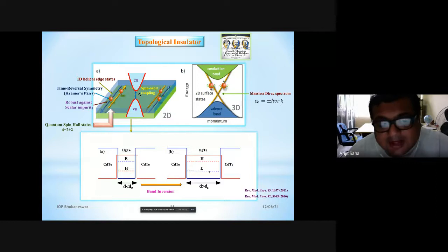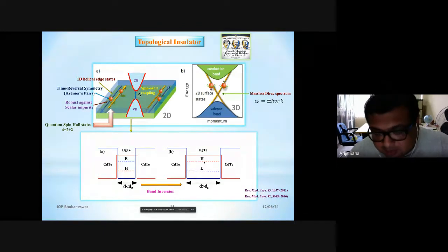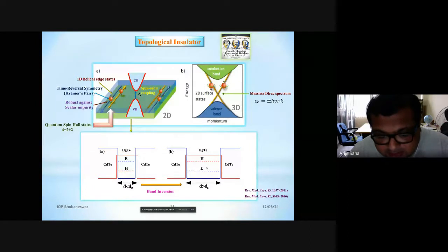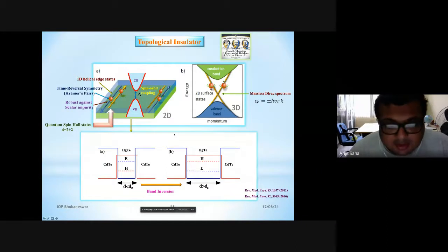But at least from the band inversion point of view, you can see that something cannot invert without going through a zero. That means when you have a band inversion in this system, you will have a zero mode. So these edge modes or surface modes are the zero modes, which exactly appear at zero energy.